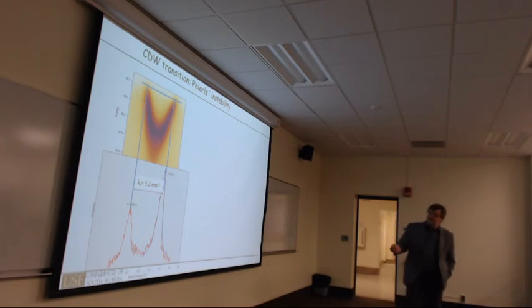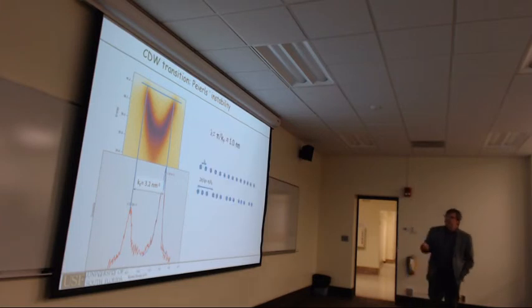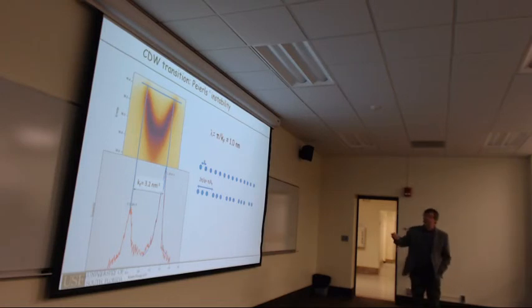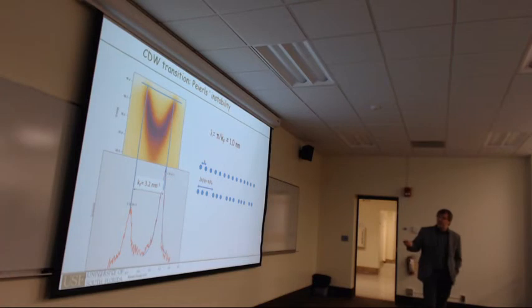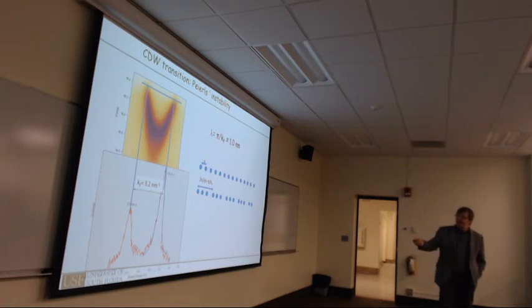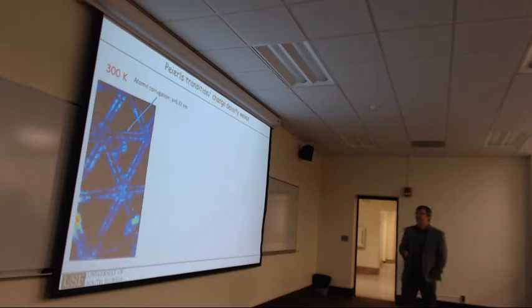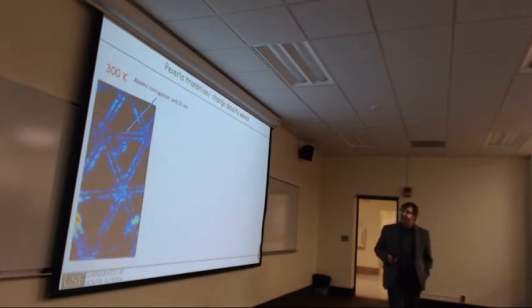First, we can measure the Fermi wave vector kF in our sample. So this is the band gap state. It's very simple. Then from that we find the periodicity we would expect in real space. That's around 1 nanometer in this case. So meaning that our lattice constant should distort to around 3 times the lattice constant in this particular case. Now, let's see if we get that.